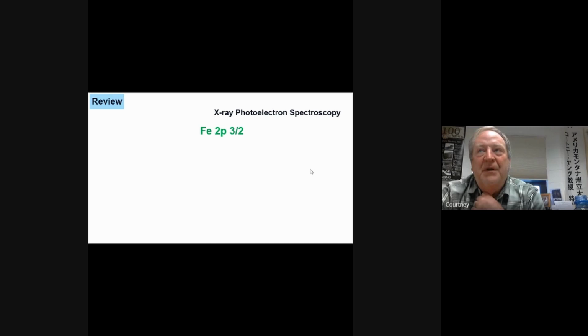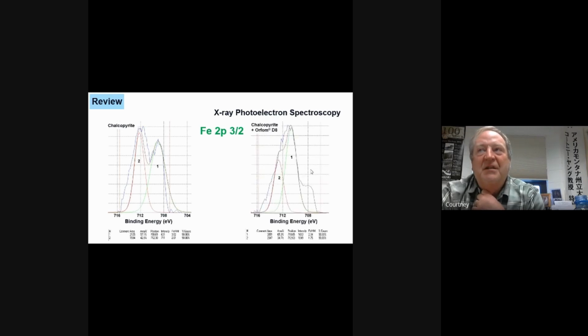So let's look at the iron 2p, and we're going to see the same thing. In this case, we're going to look at peak 1 here, and you can see that moderately compares, it's a little bit less in height, but over here, all of a sudden it's greater in height. When we look at that peak position, it's 709.01 electron volts here. It's 710.65 over here. In this case, it's plus 1.64 electron volts difference, and that's telling you that the iron 2 is oxidizing to iron 3 in the presence of Orfom D8. So Orfom D8 is causing the copper to reduce and the iron to oxidize.